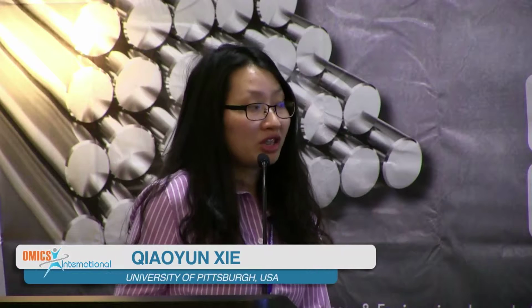The main toughness mechanisms observed are crack deflection and crack bridging. Crack deflection is the interaction between the cracks and the carbon nanotubes, where the interface has a relatively lower toughness than that of the crack propagating through the reinforcements. But crack bridging is crack propagation perpendicular to the direction of the nanotubes, in such a way that the nanotubes stretch freely along the cracking surface, which restrains the crack opening and reduces the driving force for crack propagation. They are consistent with the perpendicular cracks reaching the interface and propagating along the interface rather than cutting the grains.